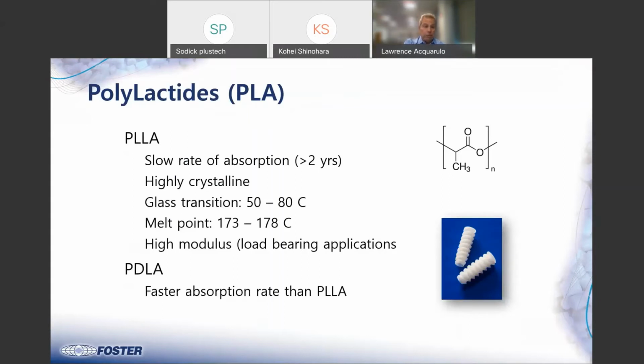Corbion is basically in the saccharide business, so they developed a lactic acid from which this polymer is made. It's a ring opening reaction, and I'm not privy to all of the science behind that, but there are two versions of it. One is the PLLA and the PDLA, and that's just a configuration of the methyl group on the chain. That has more than subtle changes in the physical properties of the material. So PLA in general has a slow rate of absorption. It could be greater than 2 years.